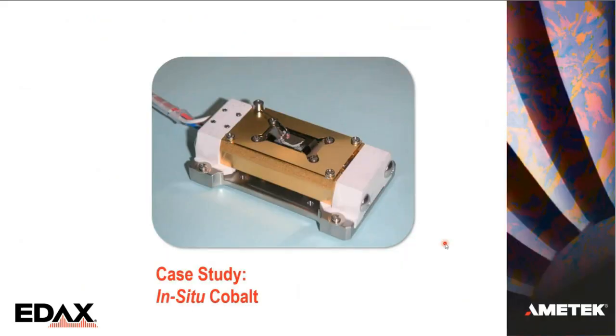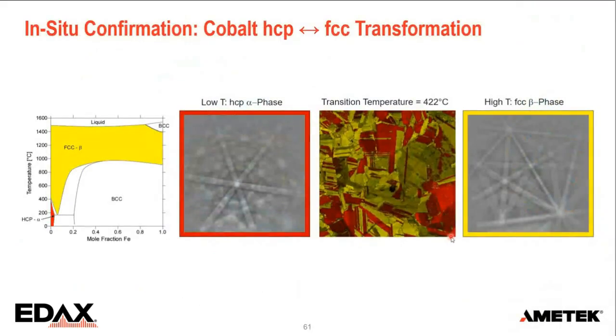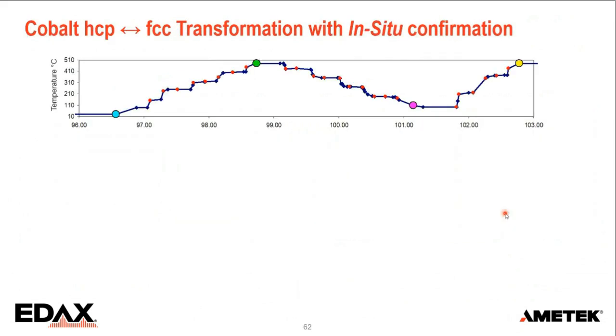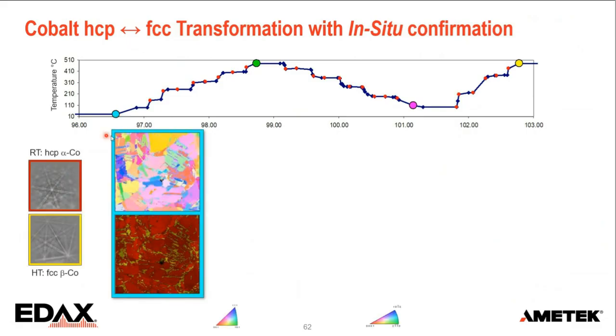Now, a few examples for that. This is a really old data set actually. It's an in situ heating experiment where we can look at the low temperature to high temperature phase transformation, going from hexagonal to cubic at around 420 degrees. When we do that, we capture some EBSD maps at different temperatures. So this is the structure at low temperature. Here we have mostly this hexagonal structure.